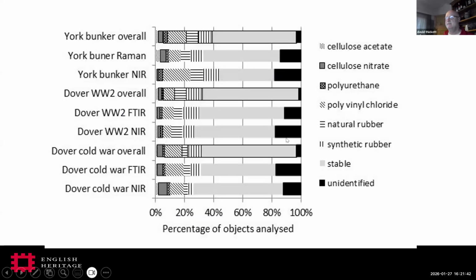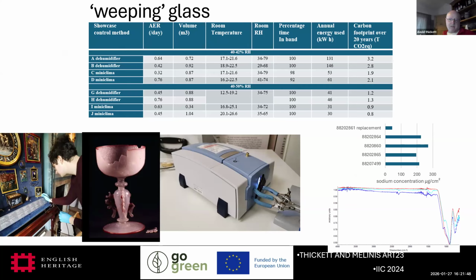And then moving on to the glass materials, about 90% of it, depending on your collection, is pretty stable, and other researchers have said that's quite safe to keep between 40 and 50%. About 10%, again, can really dramatically decay. And the recommendation is to keep this in a very tight RH band, which is very energy intensive.